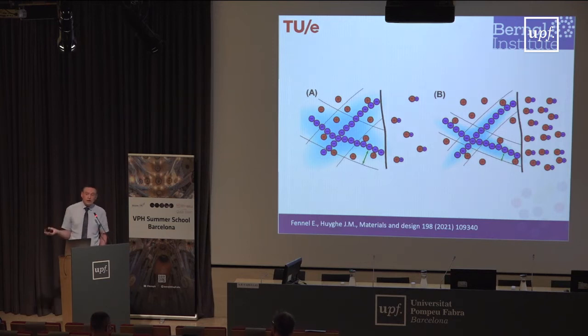So we usually think of material properties as depending on strain. Stiffness is higher at higher strain than at lower strain. Now, even if you keep the deformation absolutely constant, but this time you change the outside salt concentration, then you change the thickness of those double layers.